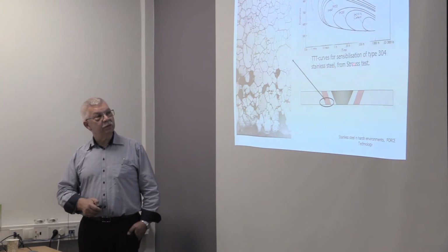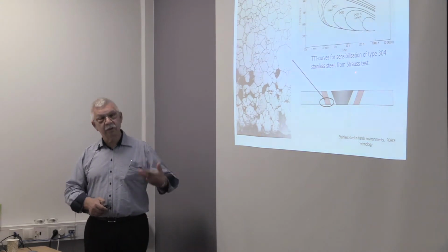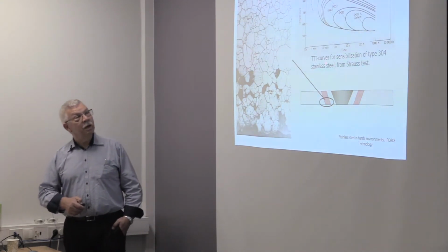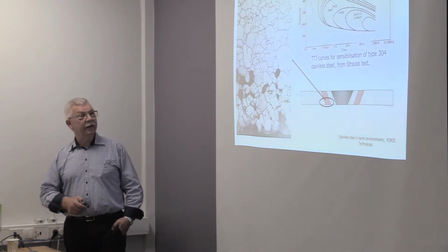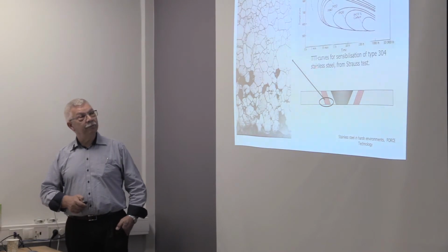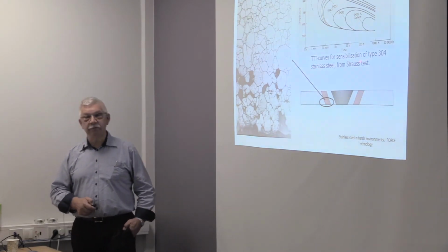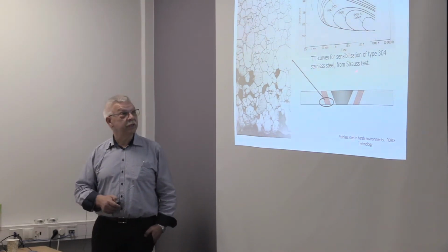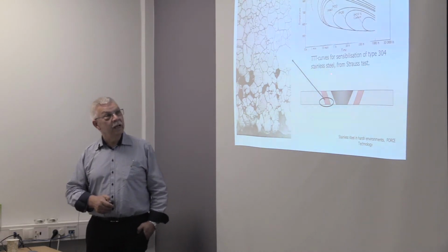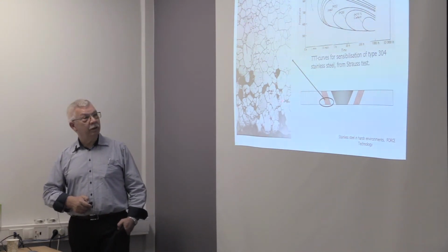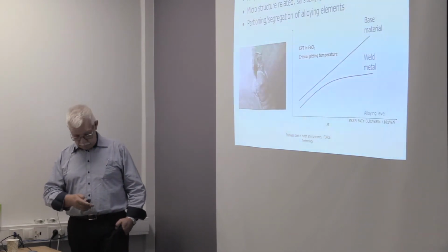And if we go into a diagram showing how big the problem is, there has been made a test with a Strauss test, which I'll describe in a moment. That's boiling sulfuric acid with some copper addition. If we are able to boil it for 24 or 36 hours in this solution, and it will not give cracks if we make a bend test afterwards, then it's good.